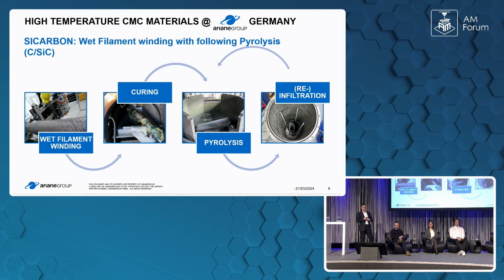So we have a wet filament winding unit, robot-assisted, as I told you. We do curing, pyrolysis, re-infiltration, or ceramization linked to the characteristic of the material. We do this several times, and we create a real carbon SiC, which is very, very resistant to oxidation and very high temperature, and with very good mechanical characteristics at high temperature.